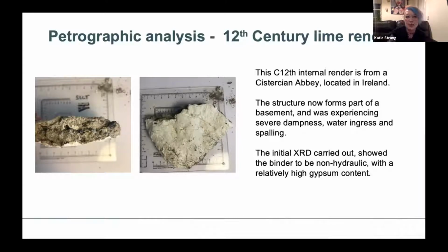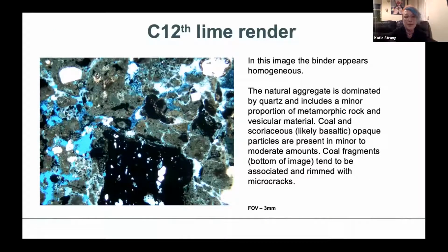lime. And we got some thin sections made of this sample because the XRD came back to tell us that essentially it was a non-hydraulic lime, so it was made up of calcite and quartz with quite a lot of gypsum in there. Now, gypsum is quite a common sulfate that forms through sulfate attack in lime mortars, and it's something you see quite regularly in thin sections. But when we're looking at a lime mortar, they're prepared slightly differently to a rock because you do have material like gypsum, which is quite soluble.